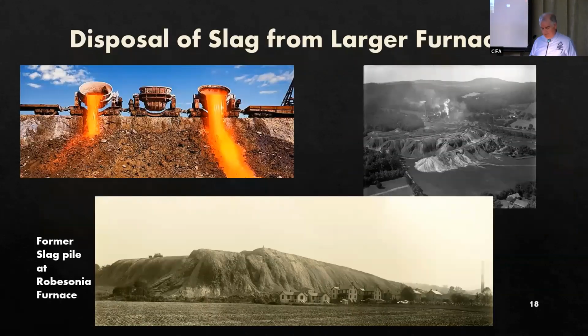Now, in later furnaces, particularly the hot blast furnaces that were larger and produced greater quantities of slag, the slag was tapped in its hot liquid form, and it was flowed into large ladles that were then either lifted by overhead cranes or were carried in special rail cars away from the furnace, where they were then dumped. Because the slag was dumped as a hot liquid, it would flow across the ground surface and find the lowest elevation, such as a creek channel.